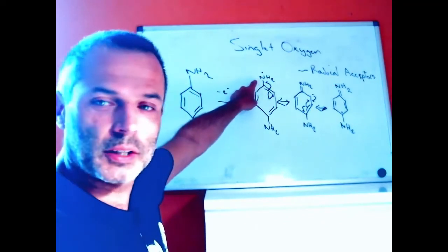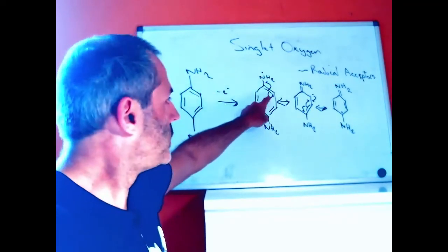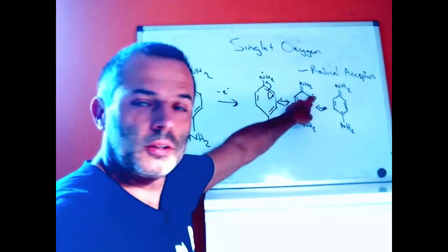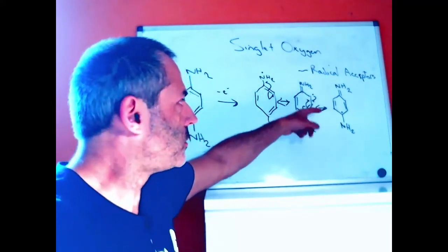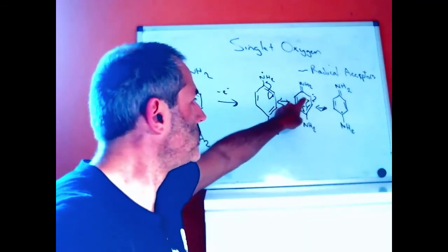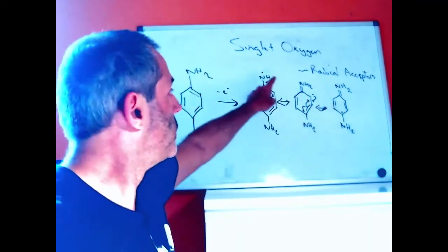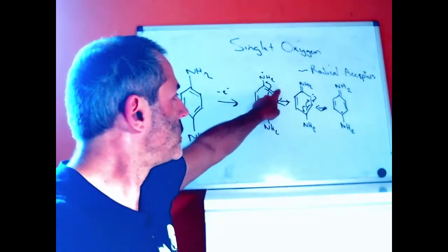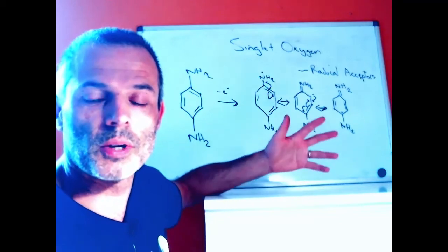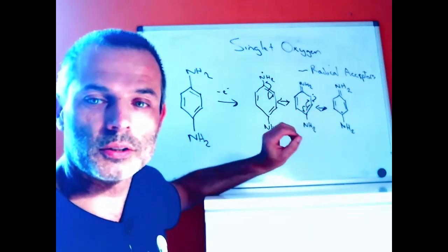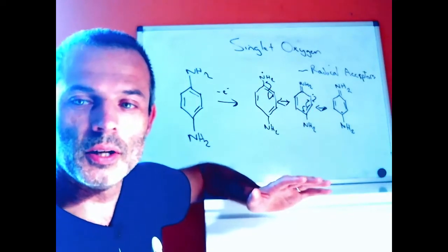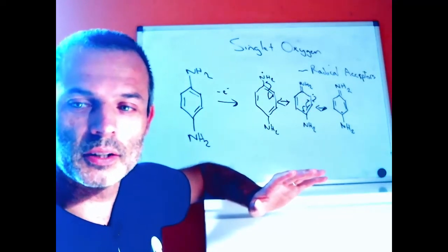It then becomes a radical on the nitrogen, but then it can rearrange to form a radical on this carbon, and it can then rearrange again to form a radical on this carbon, and obviously this one is equivalent to this one, so this radical can be on the nitrogen, on these carbons, or this one here, one of 4 centers, so the radical is effectively delocalized across 4 atoms, which makes it a lot lower in energy and a lot less likely to react.